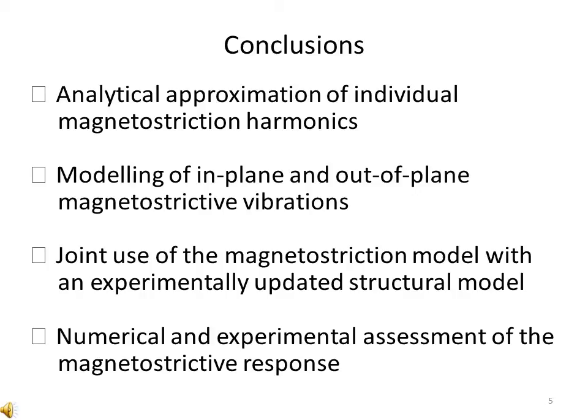In this article, a new generalized magnetostrictive forces approach is introduced for a numerical analysis of the magnetostriction induced vibration in electrical steel structures. This approach takes into account the frequency composition of the magnetostriction by introducing generally applicable analytical approximations for the harmonics. A mechanism of out-of-plane excitation is provided together with the in-plane excitation. The developed magnetostriction model is element-based and compatible with various structural models for finite element analysis. In this research, it was used together with a structural model accounting for the interlaminar contact and updated based on experimental modal analysis. An experiment featuring operating deflection shapes analysis was used to assess the numerical approach under various operating conditions.